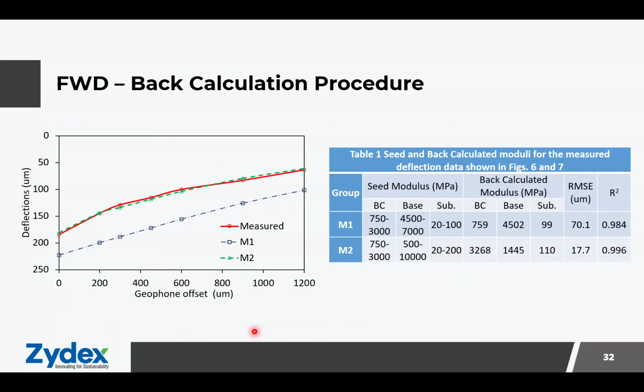Now, let me illustrate the problem associated with the FWD back calculation. Let's say we have measured the FWD bowl using the FWD machine, which is shown in the red line in this figure. On the y-axis, I have the deflections, whereas on the x-axis, I have the geophone offsets. Now, if I consider the seed modulus based upon the models that we are considering, that is the multiplier of 1000 and 750 in the relation between the resilient modulus and the UCS, the expected range of the base material will be 4500 to 7000. Or if I consider the 750 multiplier, it will be 3375 to some value. And for the BC layer, it will be 750 to 3000, which is recommended by IRC 115. Depending upon the visual survey, we can select this range. And for the subgrade, it recommends considering the range of 20 to 100.